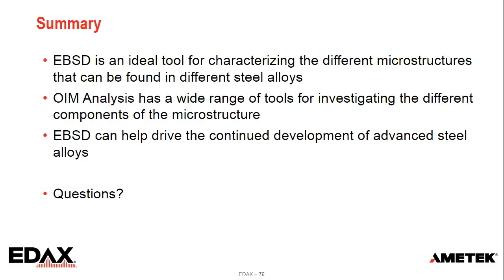There's a couple of questions here essentially talking about spatial resolution, one in terms of retained austenite and one in terms of carbides in the nanometer range. Nanometer range starts to get small for regular EBSD. The spatial resolution is probably somewhere between 20 to 50 nanometers as a ballpark. It's very difficult to describe because it will change depending on the atomic number of what you're looking at. The heavier it is, the better it scatters, the better the spatial resolution.